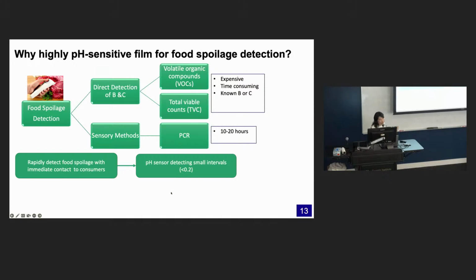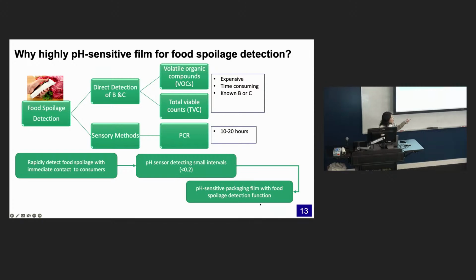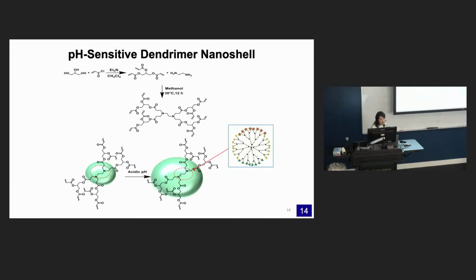So, but our film, we can make the range less than 0.2, and so finally we want to get this highly pH-sensitive film, but anyway, it's hydrophobic and food safe. So the first thing, we're starting from the glycerol. So using glycerol starting materials, so first you make the